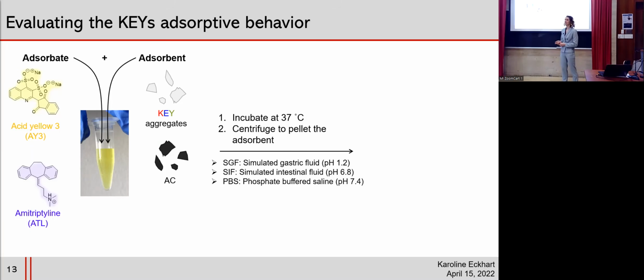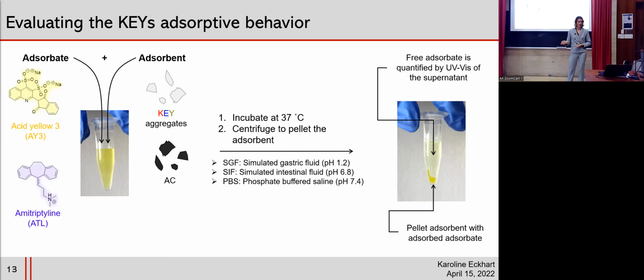And after combining these drugs, we incubated them at body temperature. And we performed these experiments in simulated gastric fluid, simulated intestinal fluid, and phosphate buffered saline, which each have different pHs and different salt concentrations that are relevant to in vivo applications. And then we centrifuged the solution to pellet out the adsorbent, which had captured the drug from the supernatant. And then we sampled the supernatant to quantify by UV vis how much drug was left over after the adsorption process.